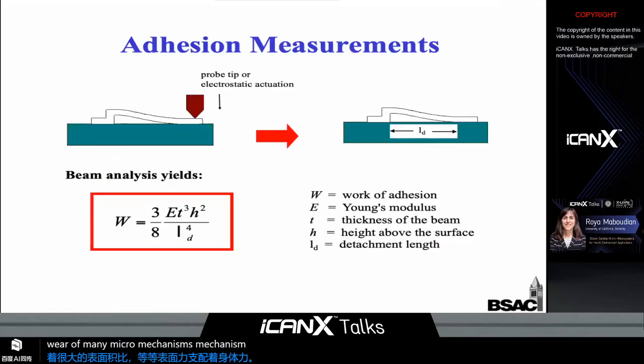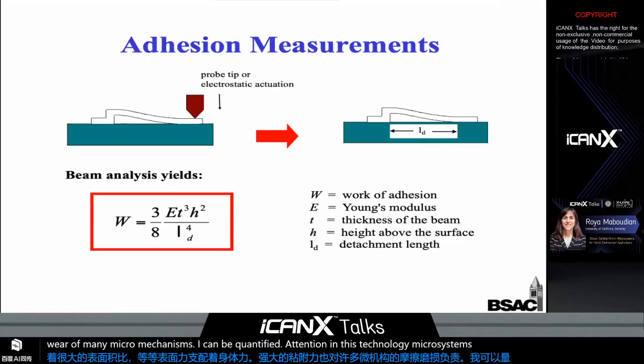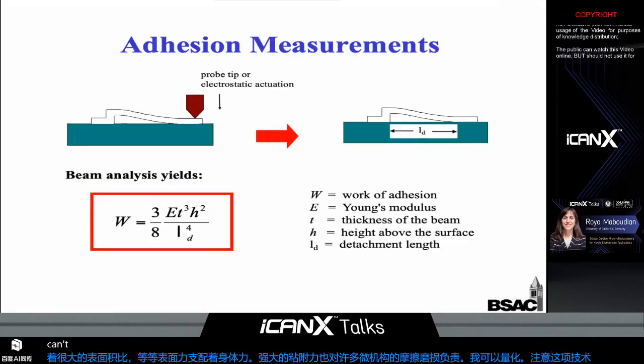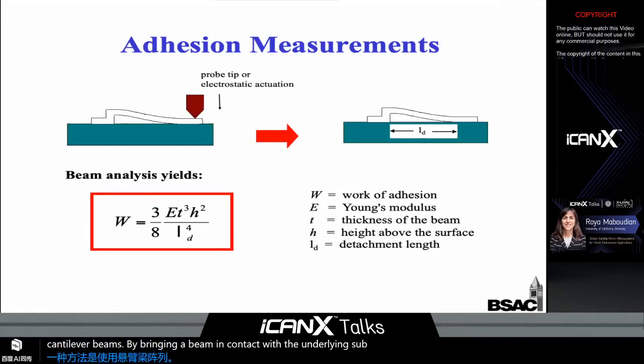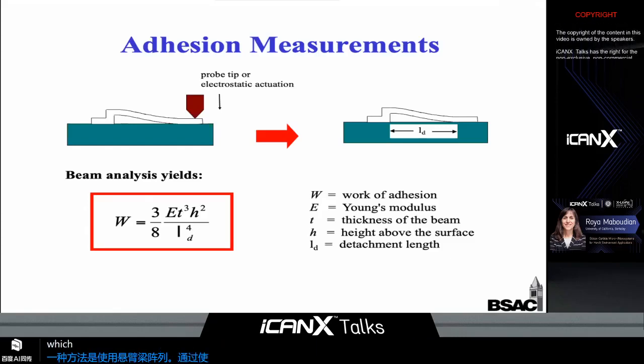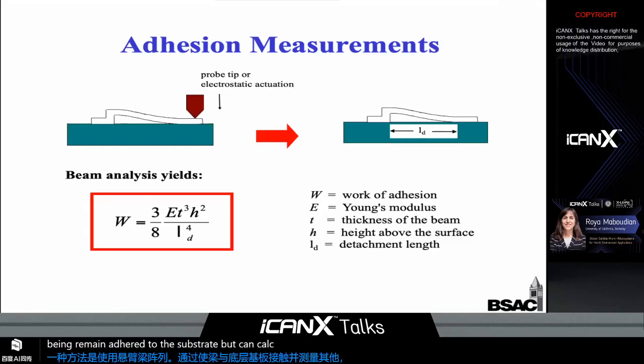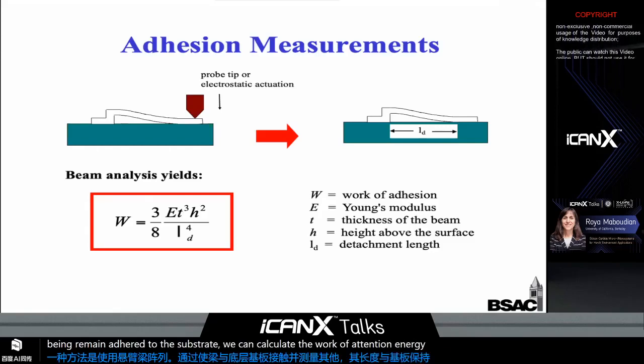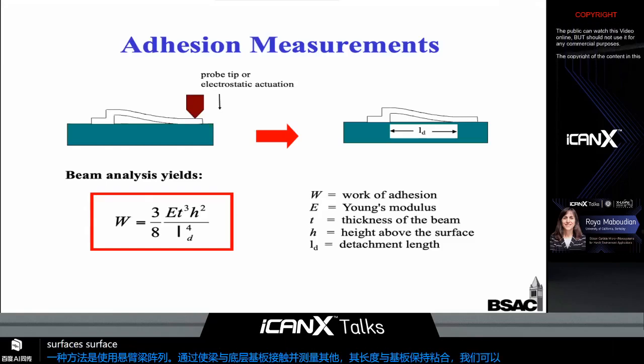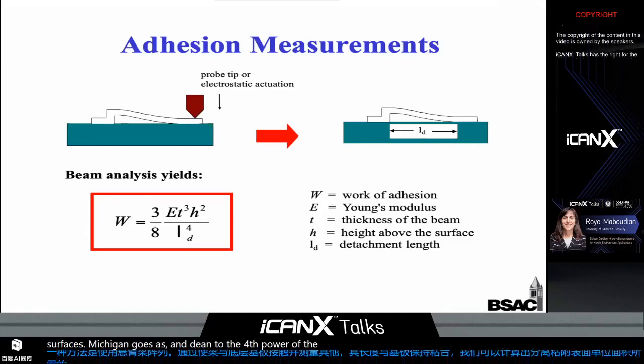How can we quantify adhesion in microsystems? One method employs an array of cantilever beams. By bringing a beam in contact with the underlying substrate and measuring L sub d, the length above which the beam remains adhered to the substrate, we can calculate the work of adhesion, W, the energy needed to separate unit areas of two adhering surfaces, which you can show goes as L sub d to the fourth power, the detachment length to the fourth power.